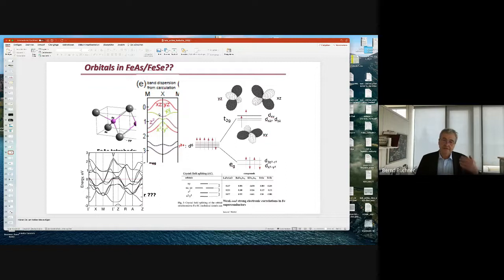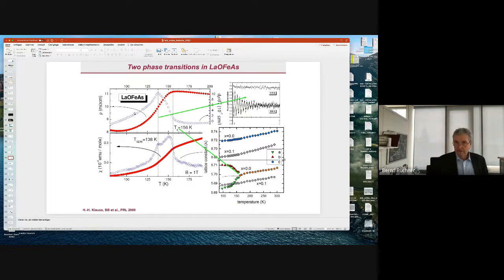And details are also not 100% clear. But it's clear that the electronic states responsible for transport, responsible for superconductivity, somehow also have some kind of orbital character. And again, for orbitals, we know they are connected to lattice directions. They are strongly connected to lattice degrees of freedom. And that is also, let's say, the experimental signature in these iron-based superconductors, that these orbitals play a role, that we have an instability of the lattice.